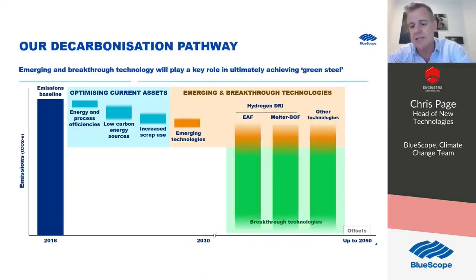And a way to do that is that there's an interim step called the melter, which is a process that we have in our New Zealand steel operation, which we can then use to remove the slag out of that DRI product and then move that onto what we currently use, which is a BOF. So at the moment, most of the world uses a blast furnace BOF process, which is a basic oxygen furnace. And if we're able to do that, then it actually means that a lot of infrastructure in steelworks won't need to be rebuilt because a lot of steelworks already have that BOF set up. If we had to convert to EAF, we're looking at a couple of $2 billion to change over as well.